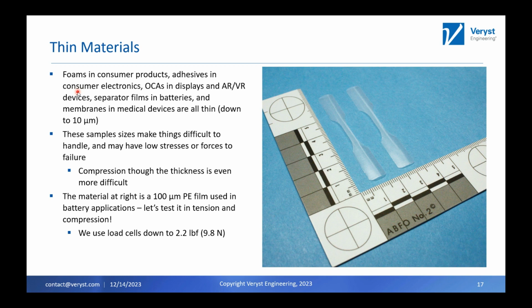This one is a polyethylene film that we got that was 100 microns. This is really targeted at battery type applications, because these types of films are used there fairly extensively. So we're going to do both tension and compression testing of this. For tension, we're going to use a normal type 5 dog bone, but it's 100 microns thick. Then we're going to do compression in the through thickness direction.